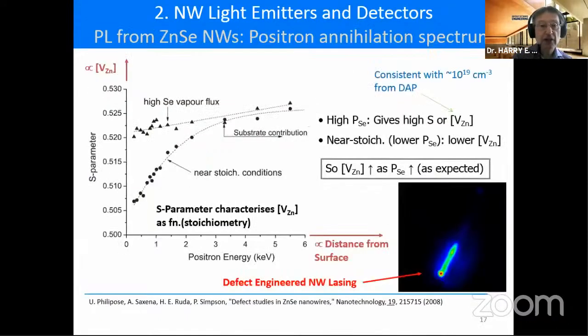And just to finish, the last part of this puzzle would be those vacancies. If you do positron annihilation spectroscopy, which is looking at positrons being trapped on the vacant zinc acceptors through the S parameter, as shown in this figure here, we can look at it, and the surface would be the 0 on this scale. Distance from the surface would then be measured from there. You can see that high selenium vapor fluxes give us the highest vacant zinc concentration, as you expect, and obviously lower otherwise. So everything is quite consistent with that.